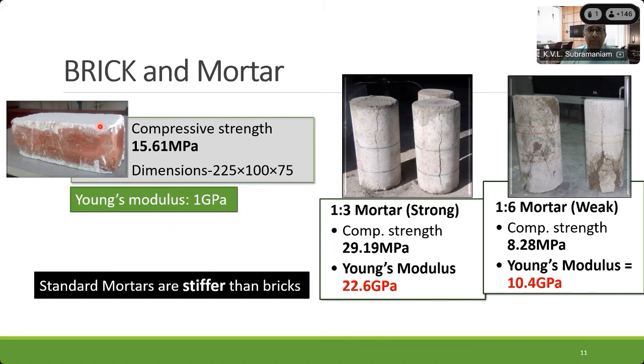But here, what we are finding with the bricks that are now coming in India is that the bricks are strong. They're adequately strong. They're 15.6 megapascal in compressive strength, but they hardly have any stiffness. They're extremely soft. So now we are going around building masonry with this brick, which is just 1 GPa in stiffness, and mating it with this mortar, which even if it's a weak mortar, which has only 8 MPa compressive strength, is 10 times stiffer than the brick. This is the story that we're dealing with.